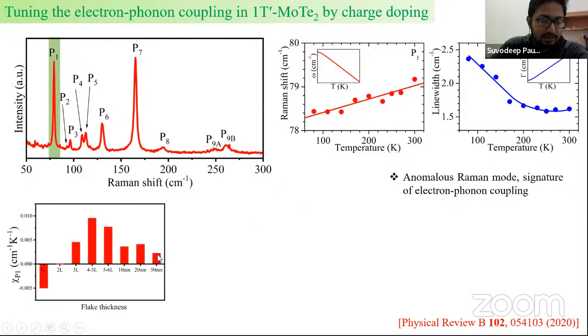And that goes like this: when we thin down the 1T prime MoTe2, we saw an increase in the electron-phonon coupling. This is essentially because of the increase in electron doping with thinning down of the sample, which has also been reported by other studies. And then we see a suppression of electron-phonon coupling for the thin layers. And finally, for the monolayer, we see a complete suppression.